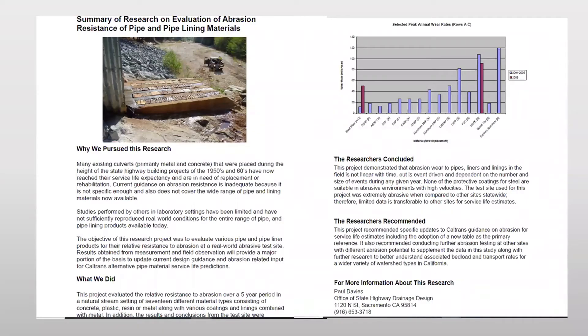To get a better understanding of the performance metrics of common culvert materials, Caltrans — California DOT — conducted a research project from 2001 to 2006 to capture and evaluate the level of resistance to abrasion of the most common culvert materials and coatings. They conducted this test at a real-world site and evaluated 17 different materials over this five-year period. The materials consisted of concrete, plastic, steel, and common pipe coatings.